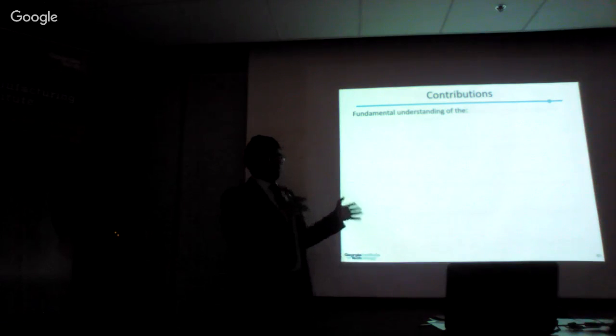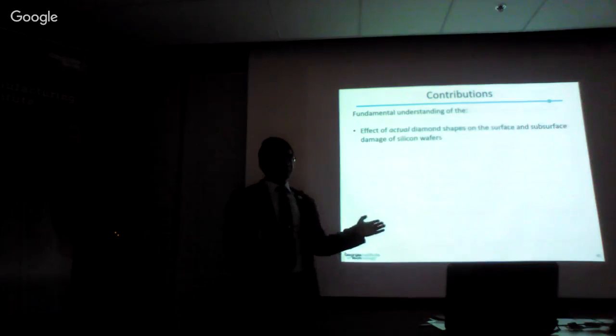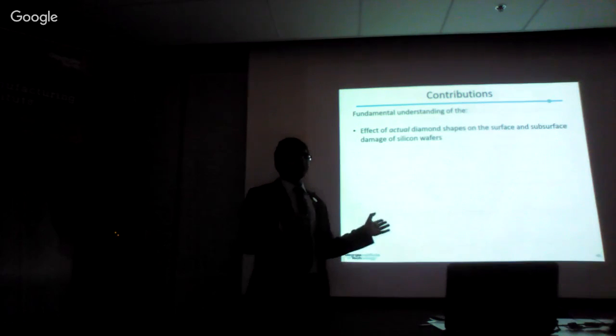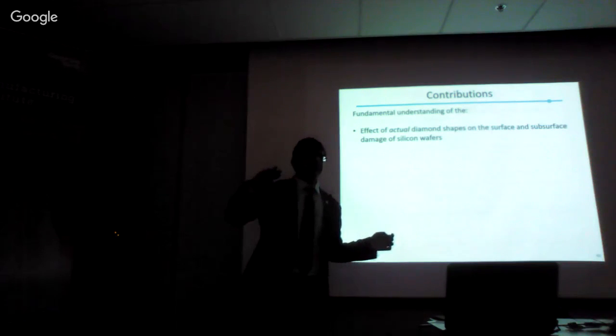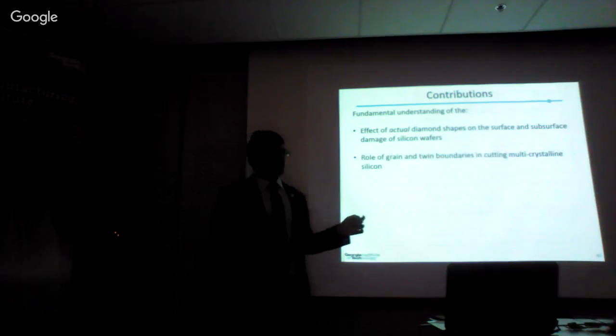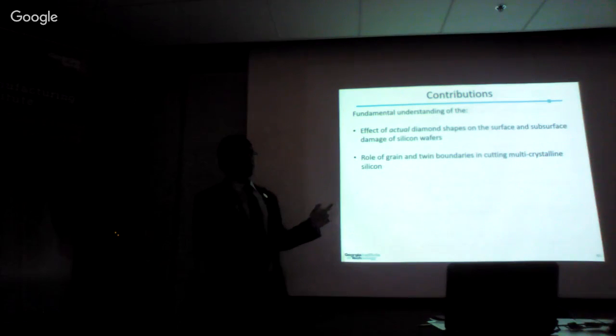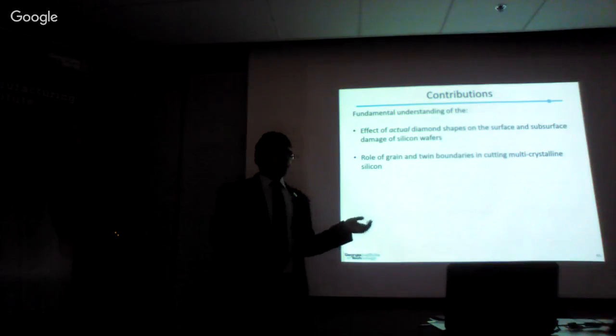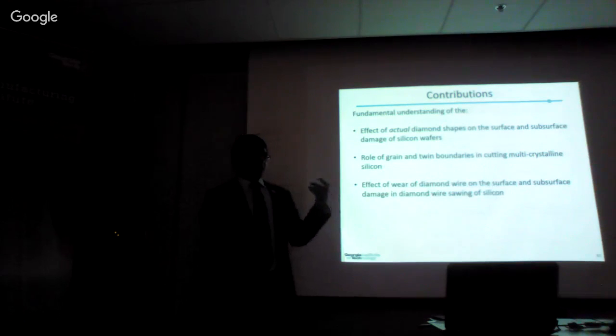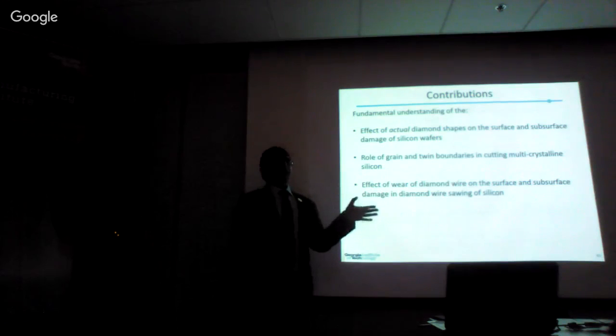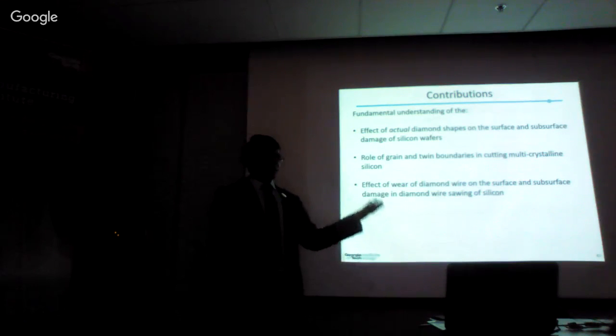So the contributions of my PhD thesis, which I found new in my research, was to find the effect of actual abrasive grit shapes on the diamond wire during slicing of silicon wafers on the surface and subsurface damage. We found the role of grain and twin boundaries with a systematic study in cutting of multi-crystalline silicon, which could affect the fracture strength of the wafers because of the micro cracks created in multi-crystalline silicon. We found the effect of wear of the diamond wire on the surface and subsurface damage, and hence the mechanical integrity and fracture strength of the wafers.